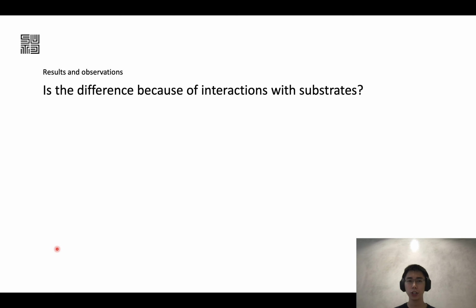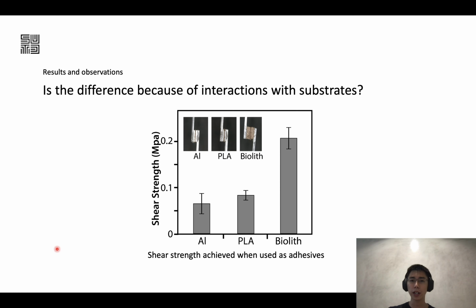So to do this, actually what we did was that we applied it as an adhesive and we tried to do a lap shear test. And what we can observe from this is that there basically isn't any difference between aluminum substrate and PLA substrate. But what else could be the reason for the difference in performance when sustaining hydraulic pressure previously?